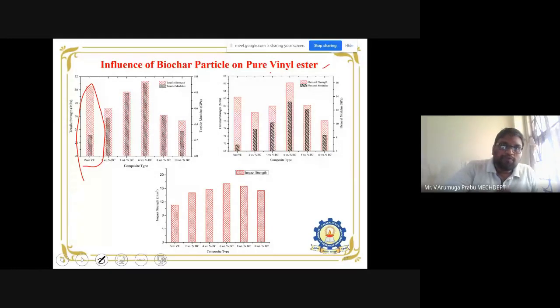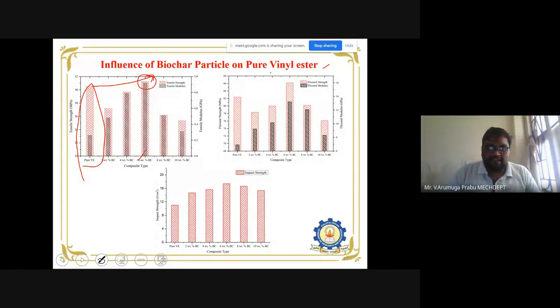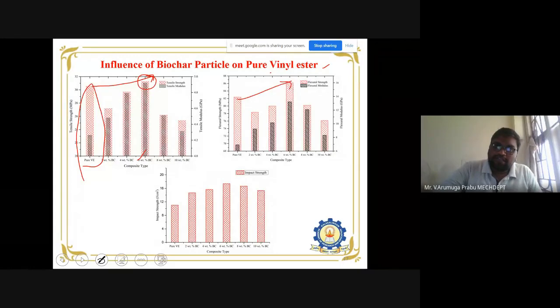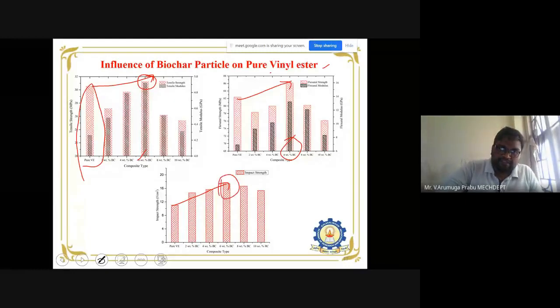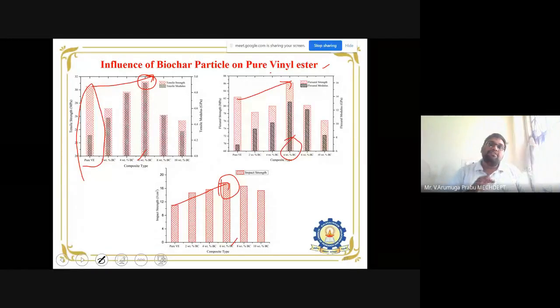So when compared to pure vinyl ester, the addition of biochar produces an enhancement in results at the 6 weight percentage. All other remaining weight percentages show a decrease in strength. If you notice the 6 weight percentage in all cases, see here also the enhancement in strength is noticed. Here also the enhancement in strength is noticed for 6 weight percentage. So among all the combinations, the 6 weight percentage biochar possesses excellent mechanical properties when compared with pure vinyl ester. Okay, so this is the proper example for a composite.